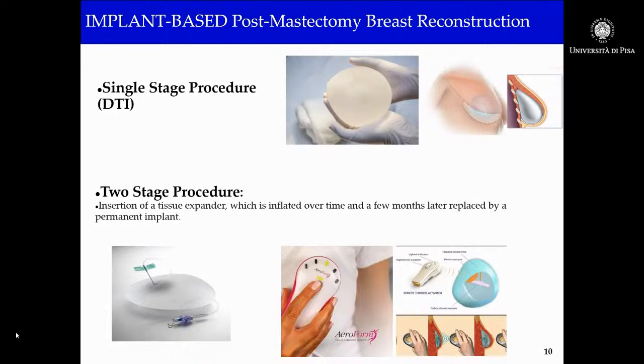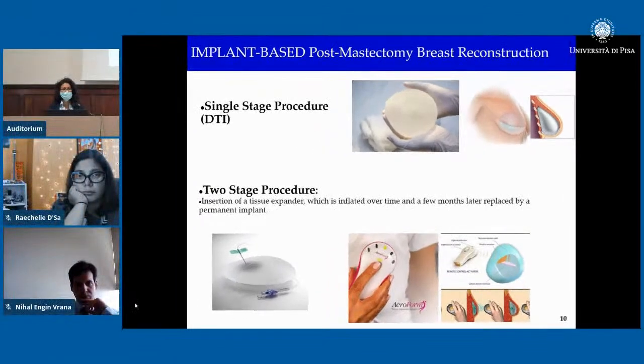This reconstructive technique can be carried out either as a single-stage procedure direct to a permanent implant, or a two-stage procedure by implanting a tissue expander that is inflated over time and then replaced some months later with a permanent implant. And because traditionally used tissue expanders require multiple injections of saline solution through the skin, that can be painful and can increase the risk of infection, recently the AeroForm device has been introduced, that is a remote-controlled needle-free tissue expander that releases CO2 from an internal reservoir, so that the patient can have a daily gradual expansion made by herself.